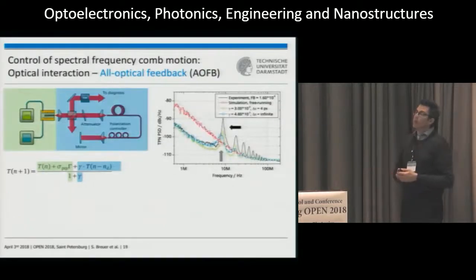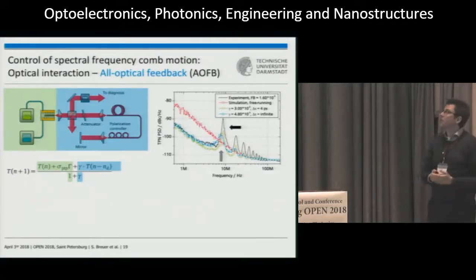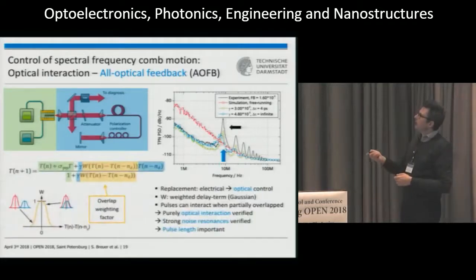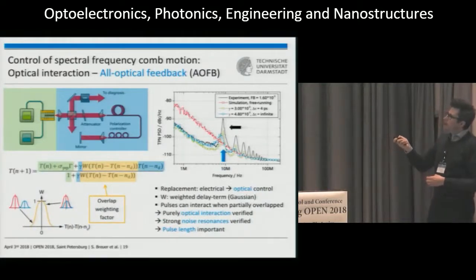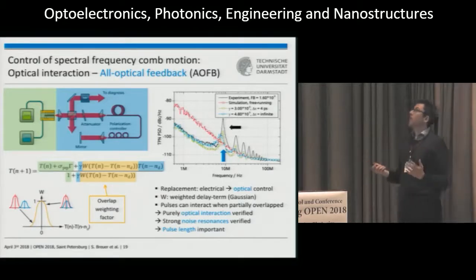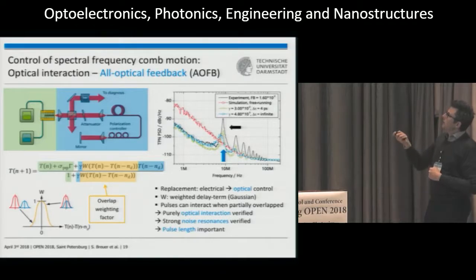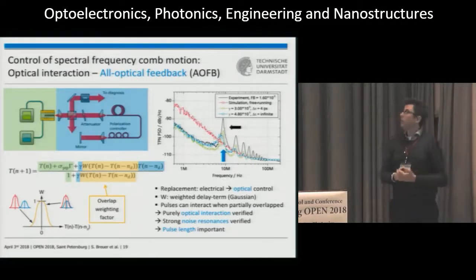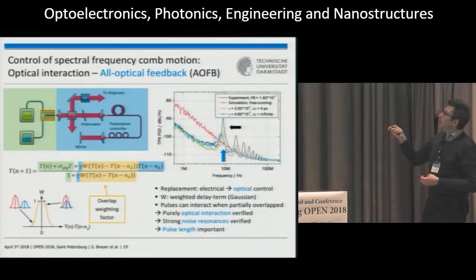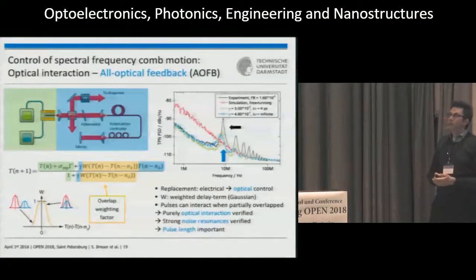Now the final step is what happens with all-optical feedback, which is immediately applicable to single section and multi-section lasers. For this, we introduce an overlap weighting factor in the formula, which just says that the pulses can interact if they are close enough to each other. This overlap weighting factor is just a Gaussian function. If you do that and look at the timing phase noise power spectral density, you get these very beautiful noise resonances that you always get with single optical feedback, exactly at the external cavity frequency of your stabilization circuit. It matches quite nicely already, but if we include the pulse widths in the model, then they are reproduced even better. With this, we can assume a purely optical interaction, and we can verify these noise resonances.